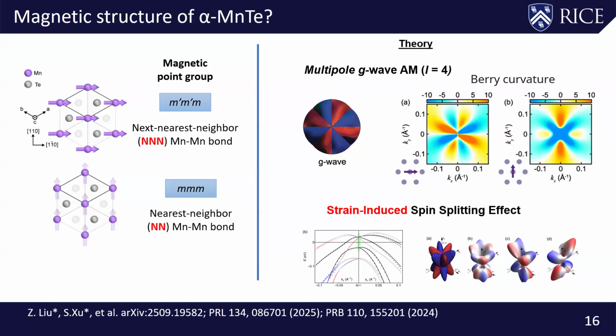If you look at this from a theoretical perspective, the reason you can potentially have this anomalous Hall from altermagnetism is this. Manganese tellurium is a simple antiferromagnet that's collinear, and if the moment is along the c-axis, then there's no problem, because the moment is going to be up and down as you go along the c-axis. But if the moment is aligned in the AB plane, then there's a problem. When the moment is aligned within the AB plane, there are two possibilities. Your magnetic structure is different in terms of the moment relative to the underlying lattice, which is entirely dictated by the spin-orbit coupling.